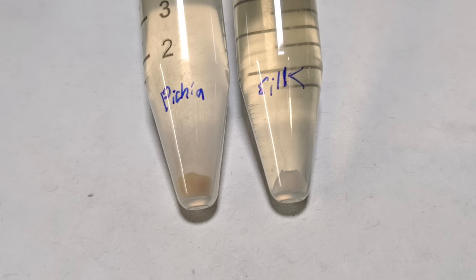Which means that the yeast really do carry the silk gene, and that weird behavior is most likely due to silk being produced. Further, when I look through the literature on the topic, silk is noted as being dramatically insoluble. So all that white goop in the tube that collects at the bottom is most likely silk-like proteins, as there's nothing else that makes sense to be there. All told, this is a ton of evidence that things are working properly.